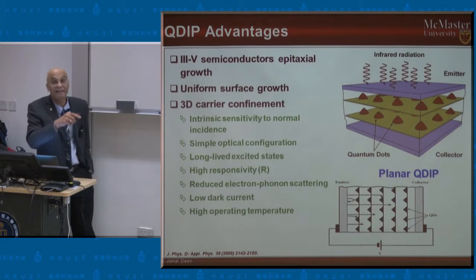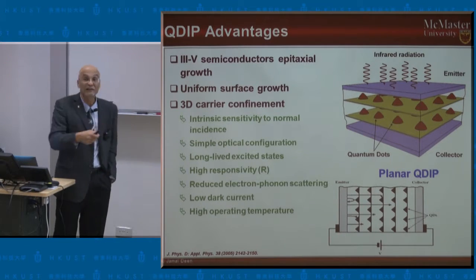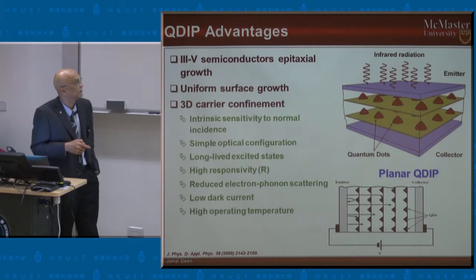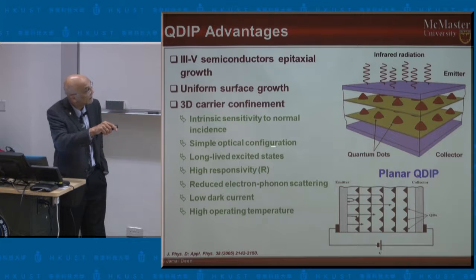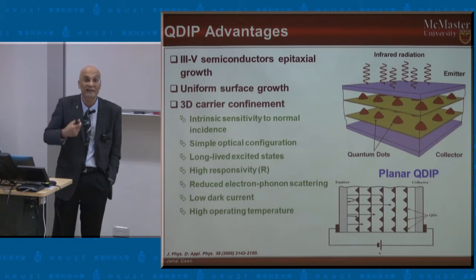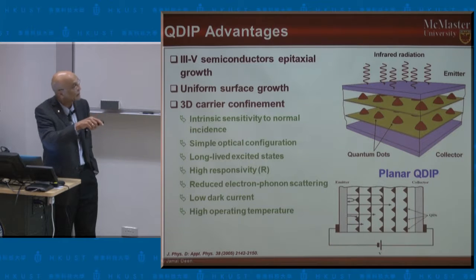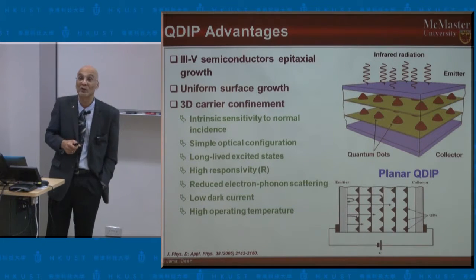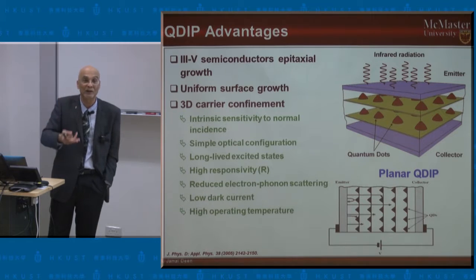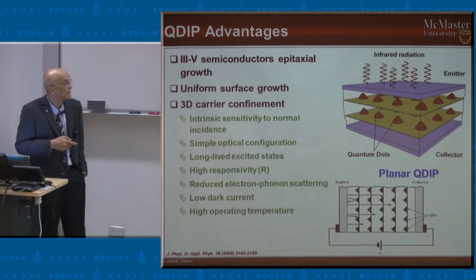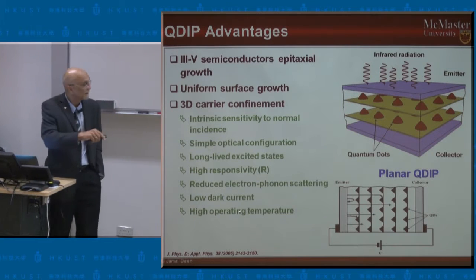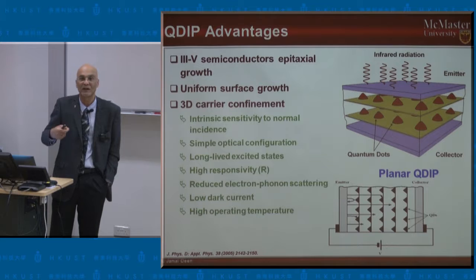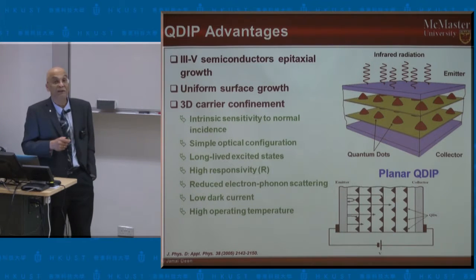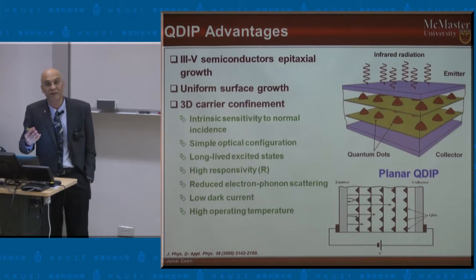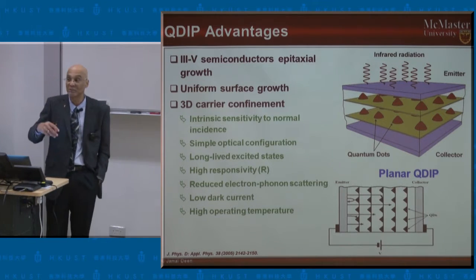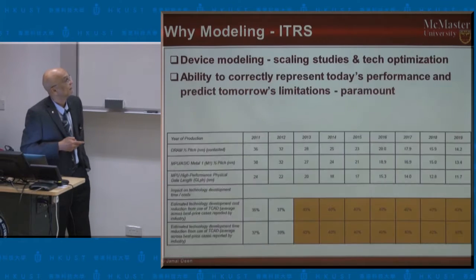Because of this intrinsic sensitivity to normal incidence, the optical configuration for coupling the light into such photodetectors is relatively straightforward. It has long-lived excited states, which are important for improving its response, leading to higher responsivity. It has reduced electron-phonon scattering, which is important because it allows us to lower the noise and improve the sensitivity and dynamic range of the device. It has low dark current, and it has relatively high operating temperature, all the way to room temperature and beyond, as compared to quantum well infrared photodetectors that were typically operated in a cooled configuration. This means below room temperature.